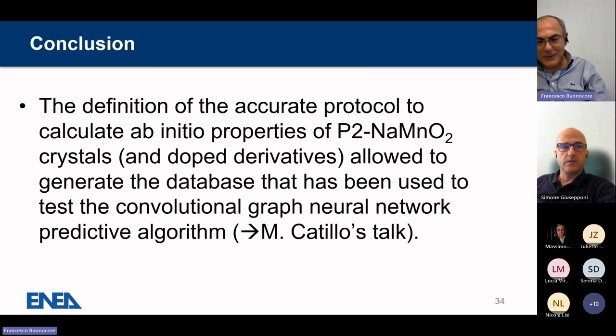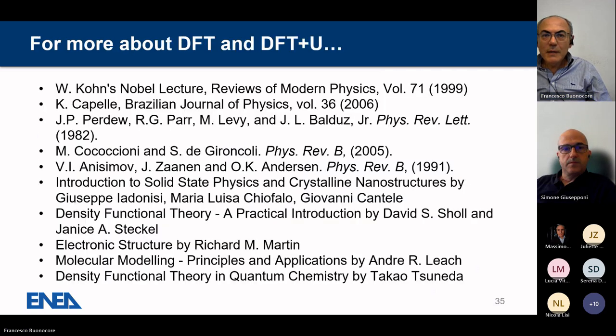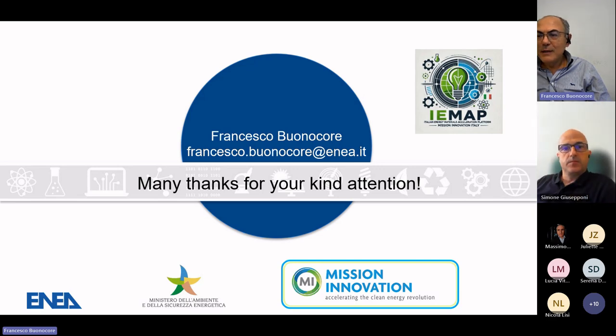And the conclusion, I finish here. I take 5 minutes more, not so much. My conclusion is that the definition of an accurate protocol to calculate ab initio properties of manganese oxide crystals based on sodium ions, also doped derivatives, allowed us to generate the database that has been used to test the convolutional graph neural network predictive algorithms. And we see that from the computational point of view, it is very time saving. If you are interested to understand more about the DFT and the DFT plus U, this is some literature you can explore. I thank you very much for your kind attention.